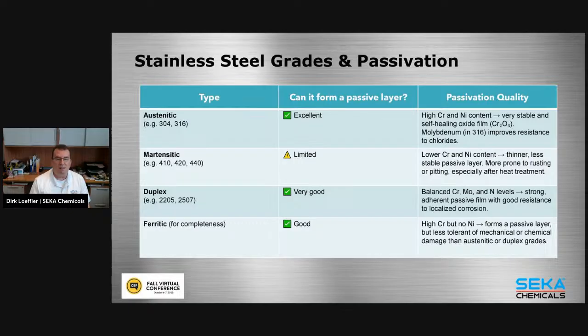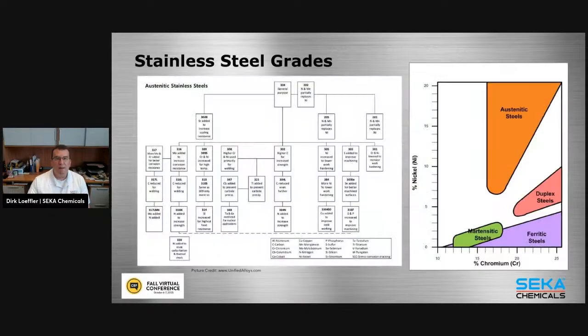We call it dairy grade stainless steel, since dairies still use bleach extensively as a sanitizer, although they're also moving away now more to peracetic acid. Martensitic has a very limited ability to form a passive layer. Duplex steels, again, have a very good one, not as good as 300 austenitic, but still very good. So for our purposes, generally, that is acceptable. Ferritic, just to make it complete here, have a good one. We generally don't find these in tanks. So just for mention purposes, we're not going to get into those.